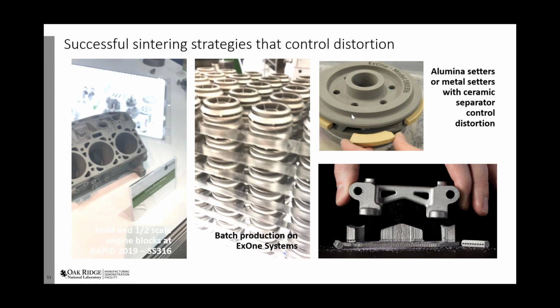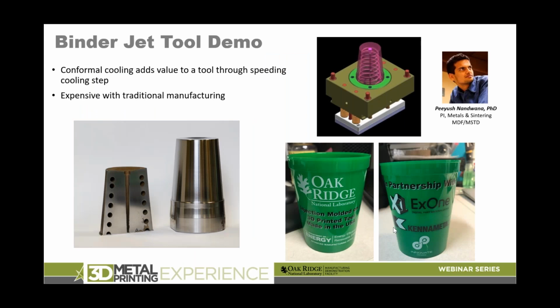You can print this alumina, put it into the critical features of your part, and then as you sinter it down, those features are maintained by the setter. And then Desktop Metal obviously has the approach where they will print support made out of the same material that you're printing out of, and then they'll put an anti-sintering agent or a ceramic between the two parts to keep it from bonding, and the idea is you can just pluck those parts right off. So lots of opportunity here in binder jet.